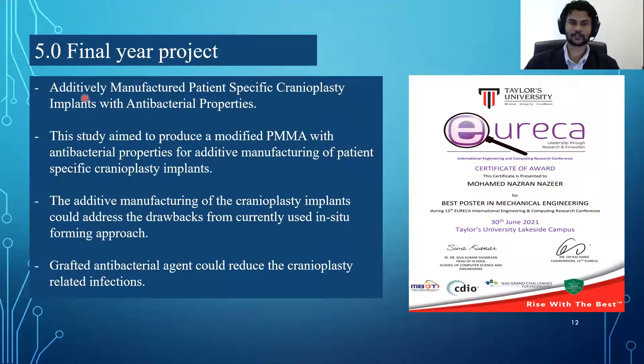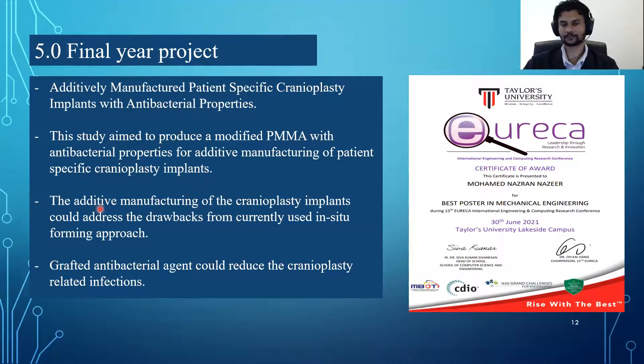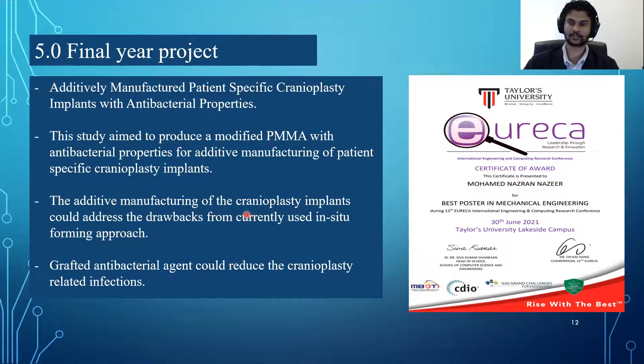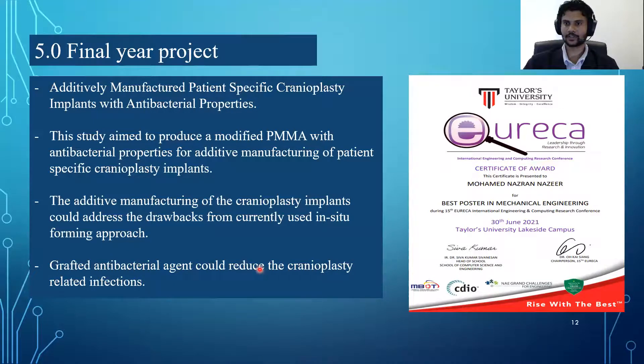The topic of my final year project is additively manufactured patient-specific cranioplasty implants with antibacterial properties. The aim is to 3D print an implant from PMMA and then chemically modify it with antibacterial agents. This will achieve two things: first, if PMMA can be 3D printed it can overcome the problems of the in situ approach — specifically the exothermic polymerization reaction that causes burn damage and the unreacted monomers harmful to the body; and second, if successfully modified with antibacterial agents, it could reduce bacterial infections post-surgery. My final year project is split into FYP1, the research phase, and FYP2, the experimental phase.